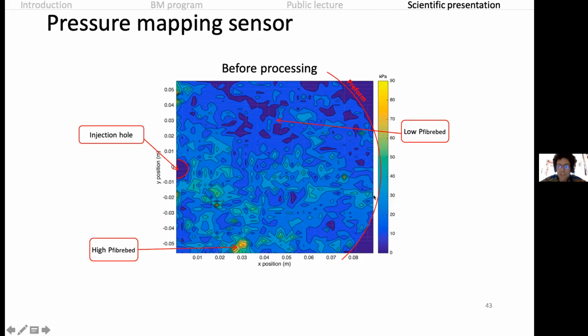At the same time, we put the pressure sensor inside the mold. So the preform was a little bigger than the pressure sensor. So here we have only half of the disc geometry. We have the vent here, and the injection gates are here, where we're going to inject the resin. And you see that the pressure inside the mat before we inject the resin is very different. Some places you have high pressure because there's a lot of fiber. There's a high pressure here because there's more fiber, and there's less fiber here, so there's less pressure. It's a very variable distribution of the material inside this reclaimed mat.